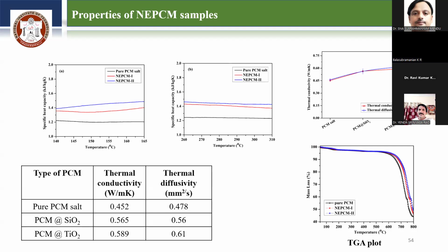Okay, so there is a slight weight loss we can observe at around 130 degrees centigrade here, and that is due to evaporation of moisture in the sample. Then the degradation of nitrate particles begins after complete evaporation of PCM, and this degradation is further continued up to 760, 750 degree